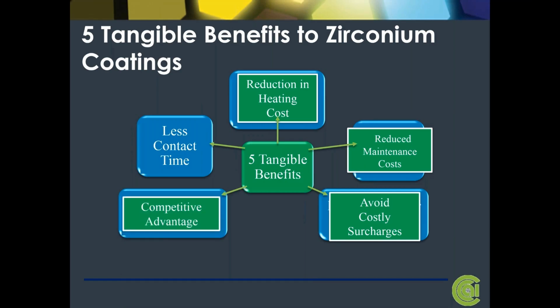And we mentioned that you're getting improved corrosion protection and paint adhesion by using zirconium. The crystal structure lends itself to a much tighter crystal. They're smaller, so they're tighter together, and it's a more tight fit, so there's less exposure to the bare metal. So you have better corrosion protection and more sites for paint adhesion. This gives you a competitive advantage over your competitors who are not using zirconium.